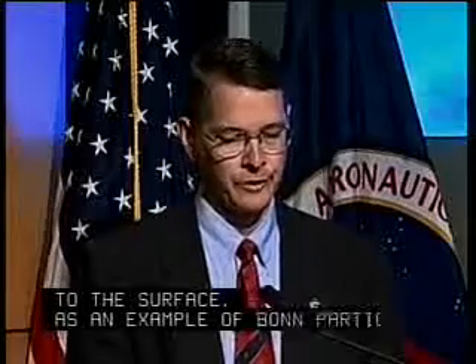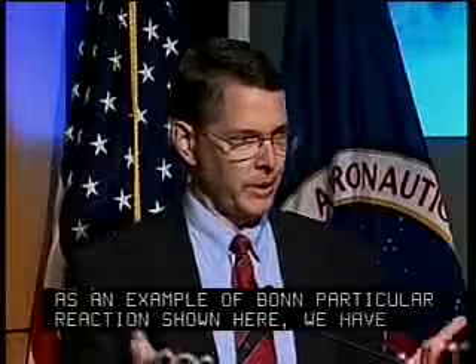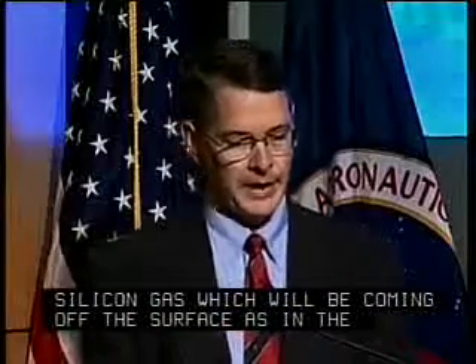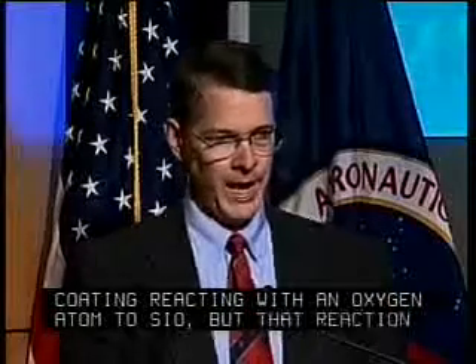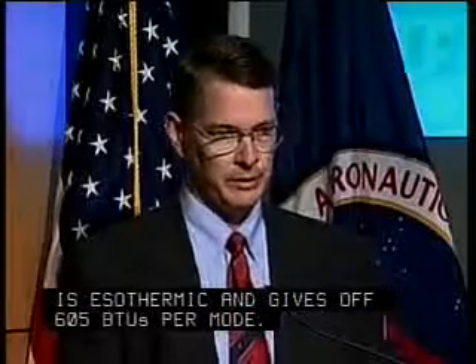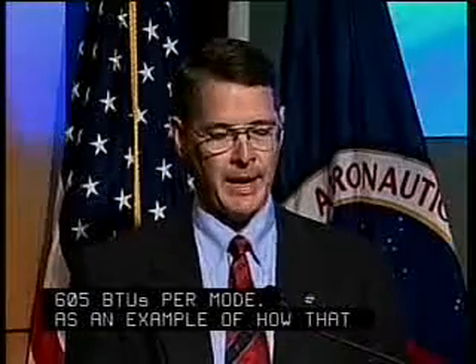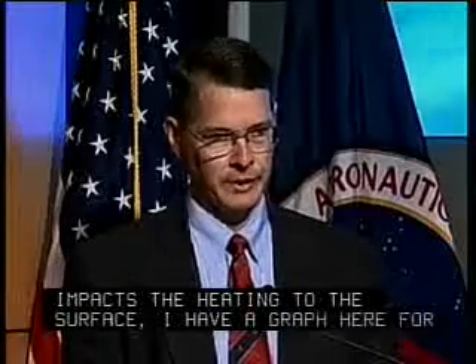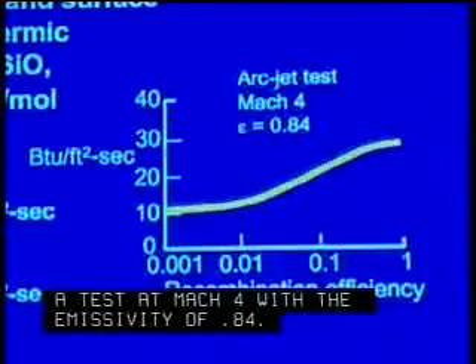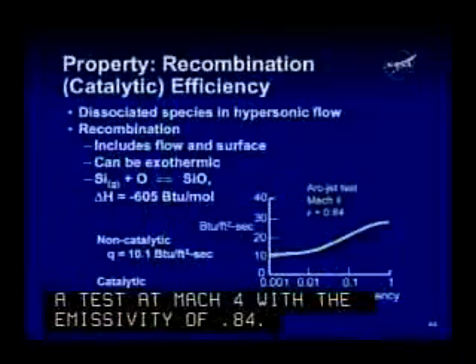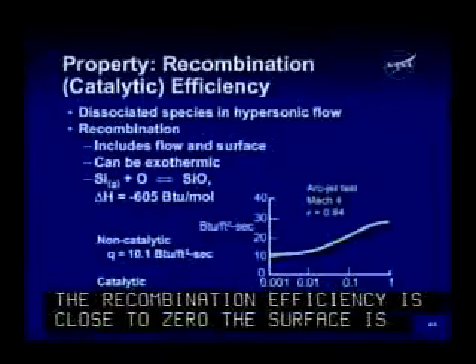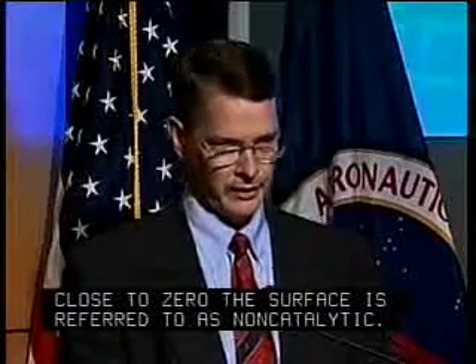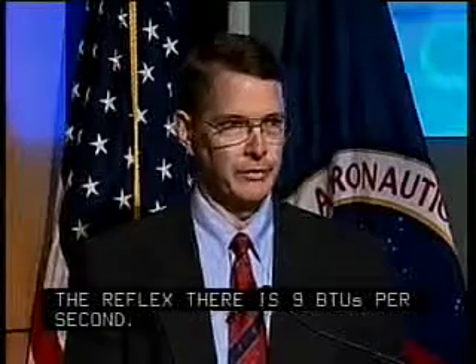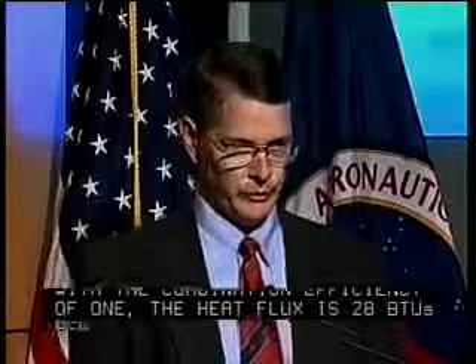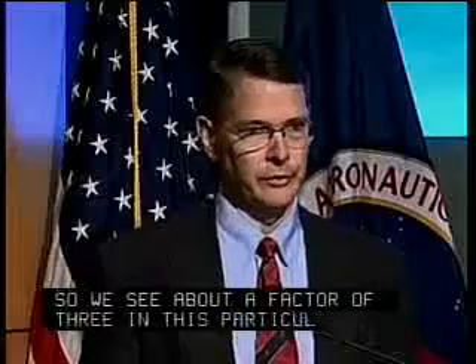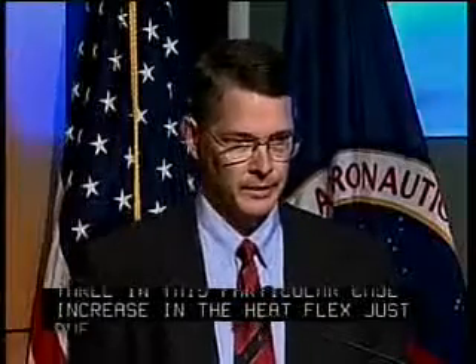As an example of one particular reaction, shown here, we have silicon gas, which will be coming off the surface, which is in the coating, reacting with an oxygen atom to form SiO. But that reaction is exothermic and gives off about 605 BTUs per mole. As an example of how that impacts the heating to the surface, I have a graph here for an arc jet test at Mach 4 with the emissivity of 0.84. When the recombination efficiency is close to zero, the surface is referred to as non-catalytic. Heat flux there is around 10 BTU per foot squared second. For a fully catalytic surface with recombination efficiency of 1, the heat flux was around 28 BTU per foot squared second. So we see about a factor of 3 in this particular case increase in the heat flux just due to catalyticity. Next chart, please.